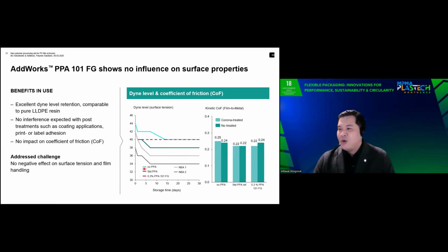With no polymer processing aid, after corona treatment we achieved a dyne level of 44, which then drops over time and stays at level 40 until 1 month. With our PPA, the red line, we start at dyne level 42, then drop to 40 and maintain until 1 month. With the standard PFAS in the market, it starts at 42, drops to 40, then drops again to 38, and stays at 38 until 1 month.